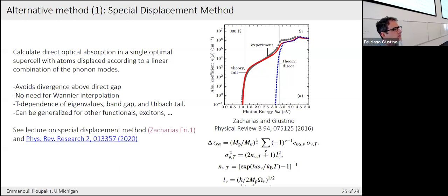That's a good question. So you say if we apply this method for doped semiconductors, right? In principle, you should get the same answer as the perturbative one for as long as you are below the threshold for direct transitions. I can think of some challenges. An advantage of perturbation theory is that because you use the unit cell, it's easier to handle cases where the Fermi surface is small.